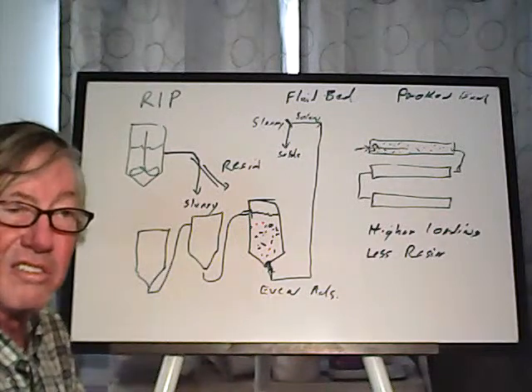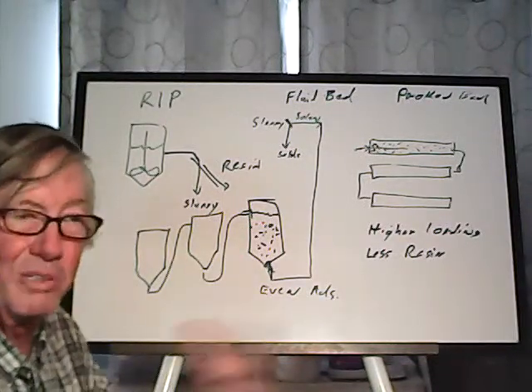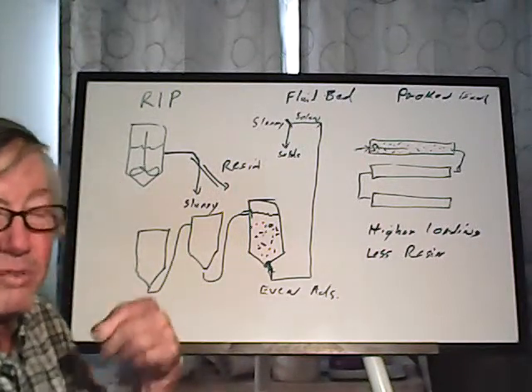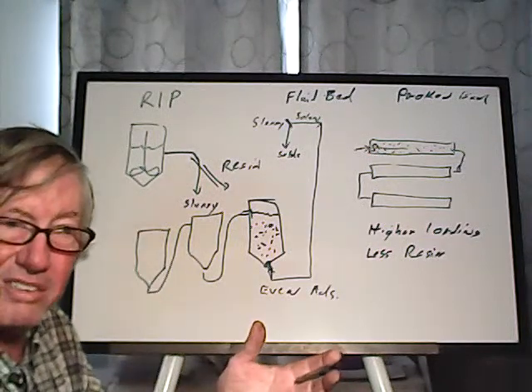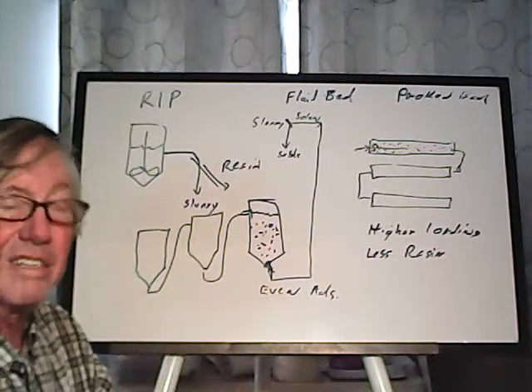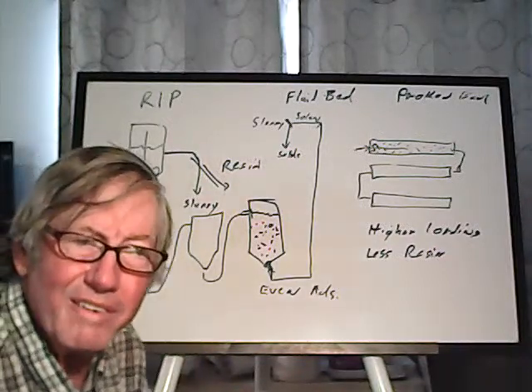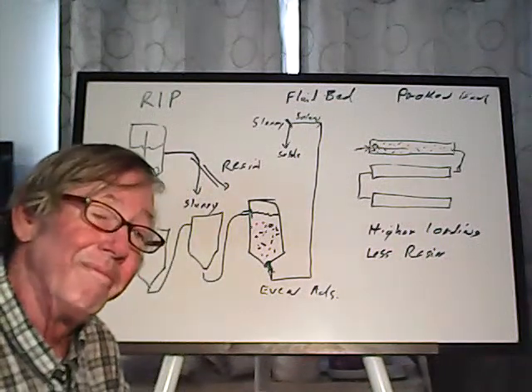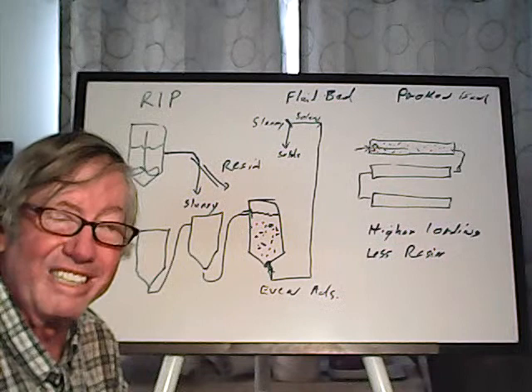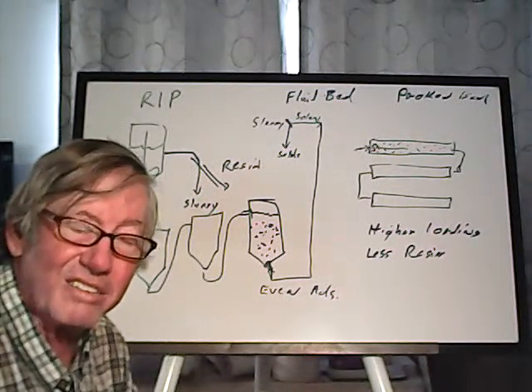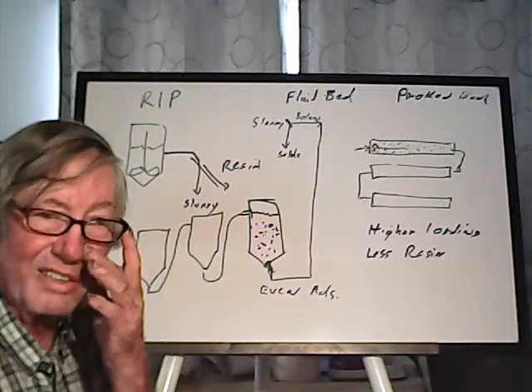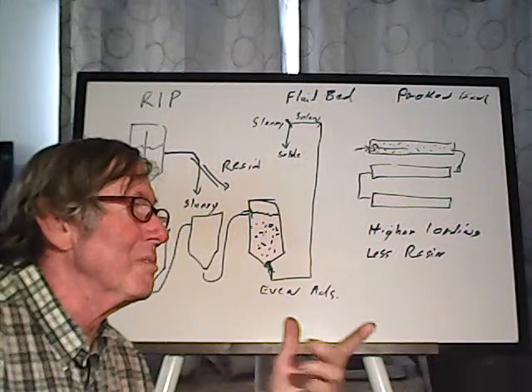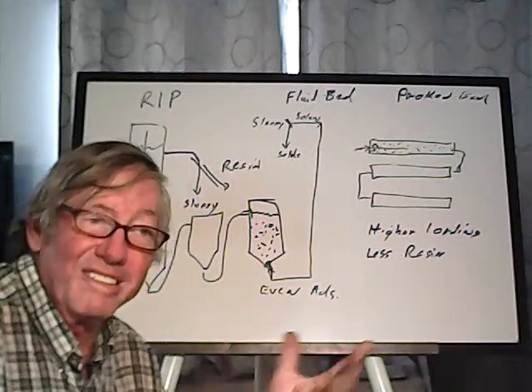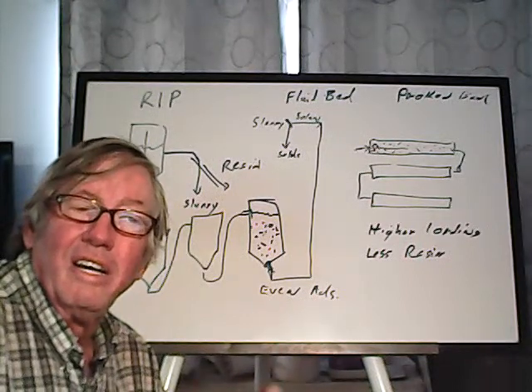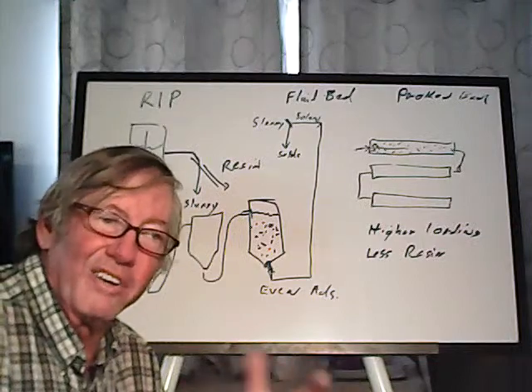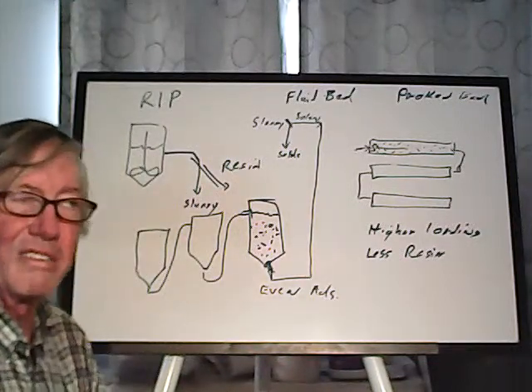But in terms of leaching solutions, there are two basic ones now on the market. The cyanide has been used for a long, long time. It's inexpensive. It's fairly simple and straightforward, but it is toxic, and in some areas it's not even legal anymore. And so they're going more to the thiosulfate leaching because it's much less toxic. You know, nothing's non-toxic. Eat enough salt, it'll kill you. As a matter of fact, I think one tablespoon will kill a baby. But toxicity is a function of concentration. And the thiosulfate solutions are inherently less toxic than the cyanide, which makes for certain advantages.